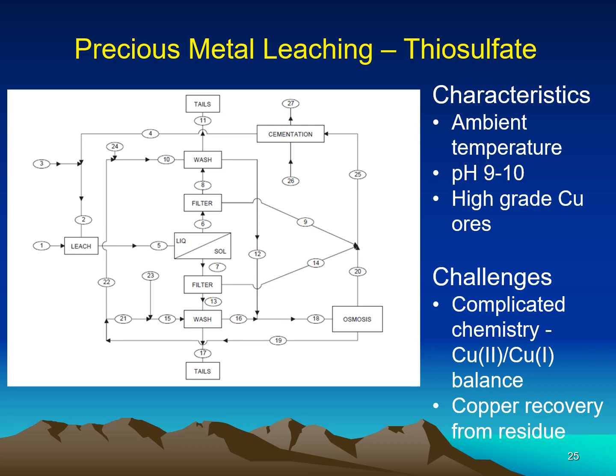And so the characteristics are ambient temperature, pH 9 to 10, and this is really for high-grade copper ores because this copper in itself is the oxidant in the process. The challenges are it's complicated chemistry. I said we have to keep a very strict control on the cuprous balance and the copper recovery from the residue that, remember, especially for the silver exchange, we have chalcocite in the residue. So we have to have some kind of a further process to recover that copper.